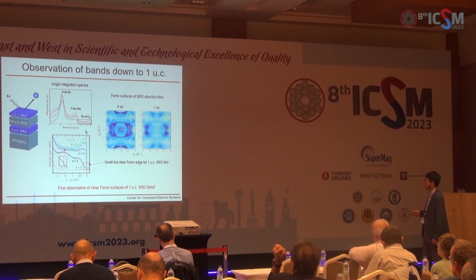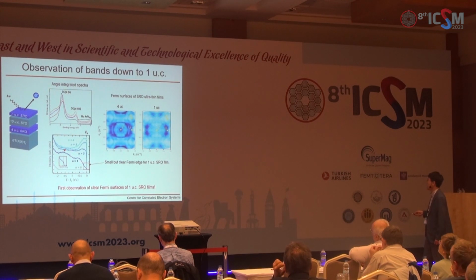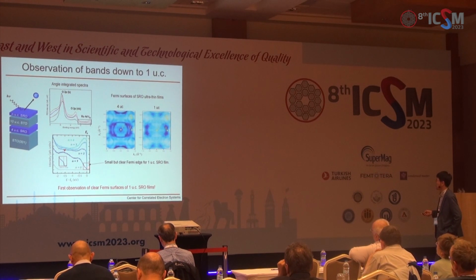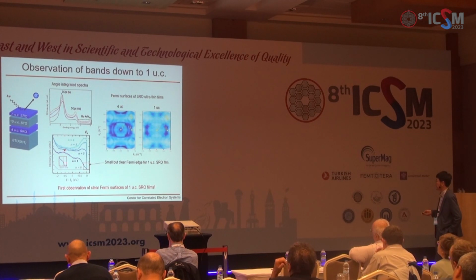Another thing to notice is that you have this hump at around 1.5 eV binding energy, and that's more reminiscent of a lower Hubbard band. As we lower the film thickness, we suppress some spectral weight at the Fermi edge, but not down to 0. We still have some Fermi edge here. Meanwhile, this lower-Hubbard-band-like feature grows.